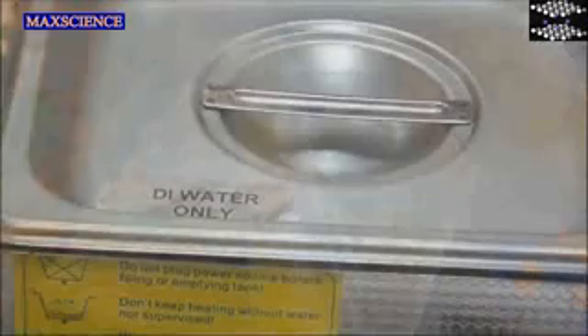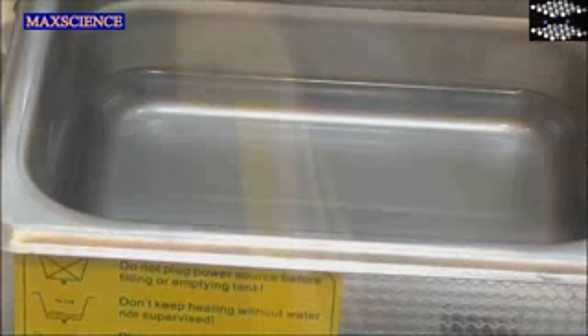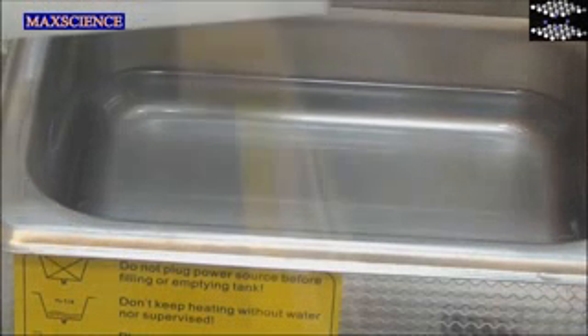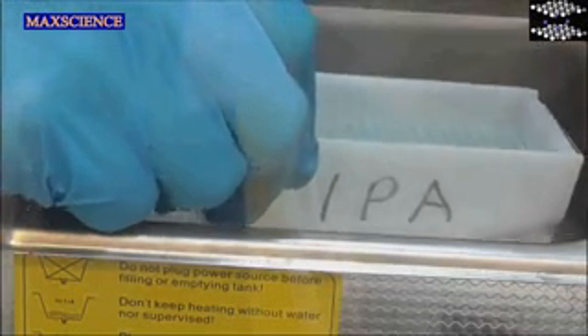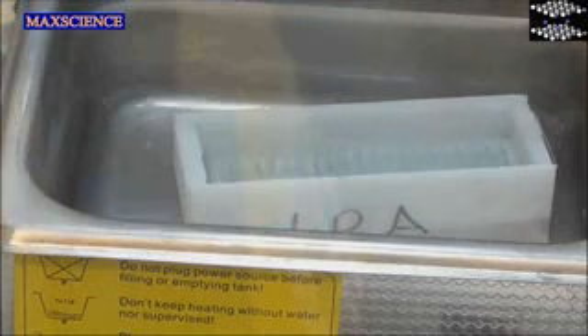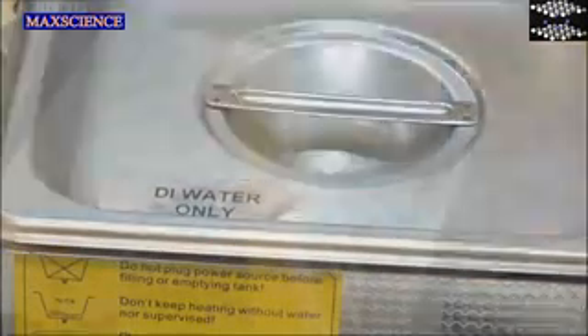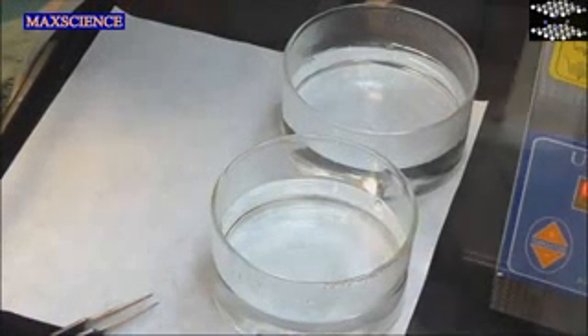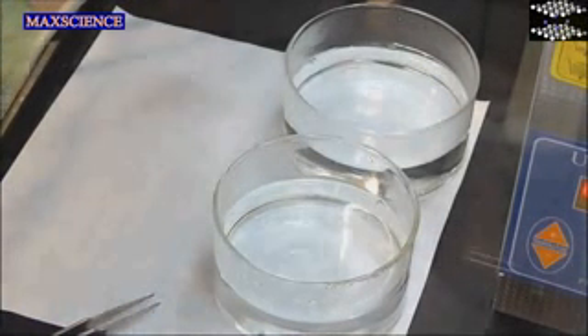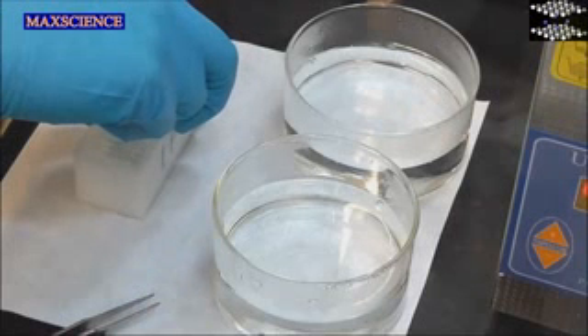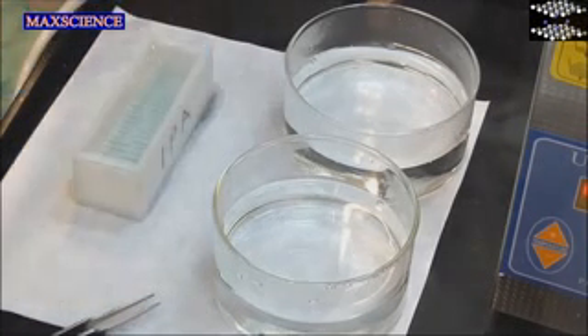The substrates are again placed into the ultrasonic bath. Make sure the DI water is close to boiling point. Sonicate the substrates for a further 5 minutes. Remove the IPA beaker from the bath and carefully remove the lid.